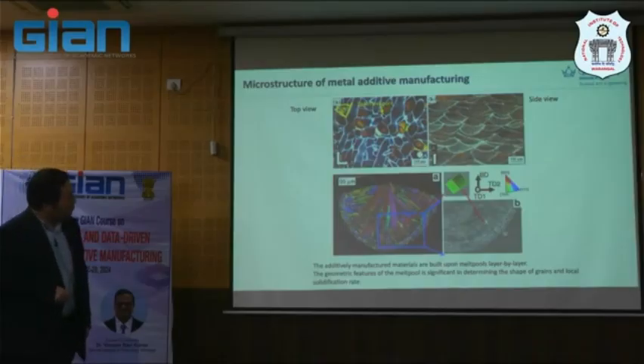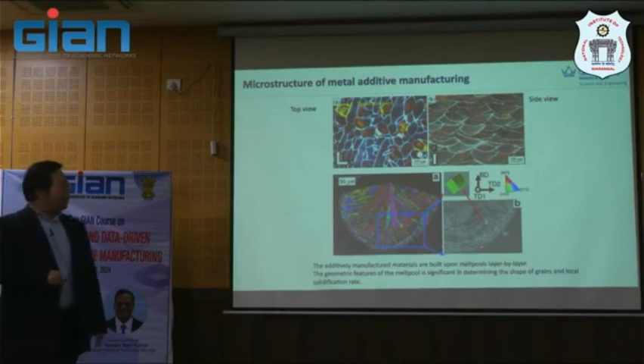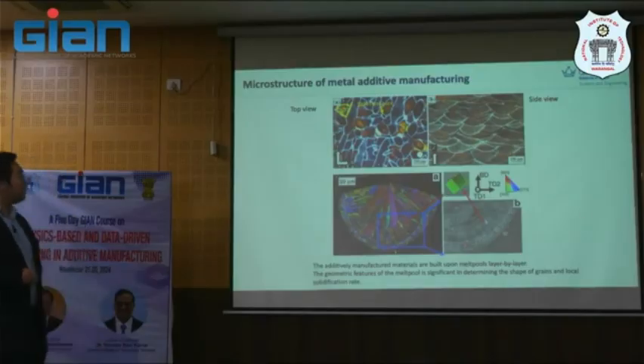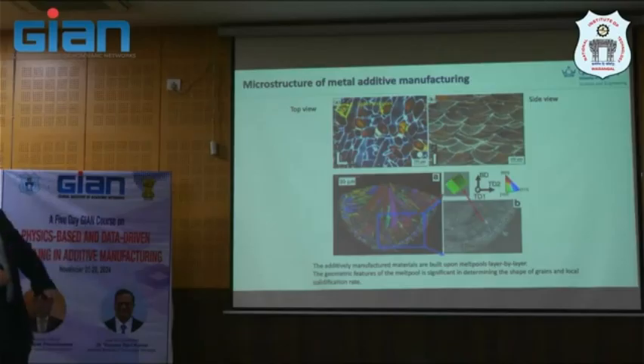But actually, if you look at this clearly and closely, we found some interesting different solute or segregation profile in the melt pool boundary that we call solute trapping during rapid solidification, which we will talk more about in the next lecture. So you will see that the microstructure across this one will be different if you draw a line across. I mean, this is a scanning path related to the microstructure you see.